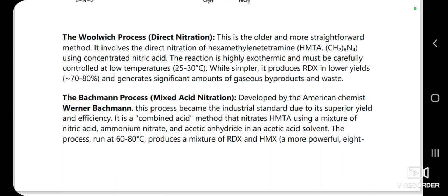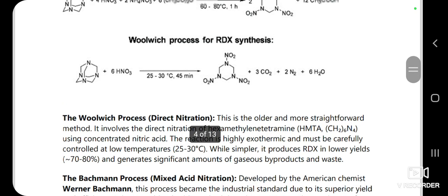The Woolwich process is the simpler and older method. It takes hexamine and attacks it with concentrated nitric acid at very low temperature, almost 25 to 30 degrees centigrade. It works, but with modest yields around 70 to 80% and lots of waste.